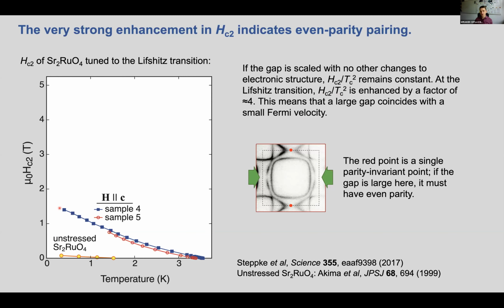So I guess my less sophisticated view of it as an experimentalist is that this rise is really very extreme, and there's nowhere else in the electronic structure, there's nowhere else in the Fermi surfaces where something rapidly is changing at this Van Hove point. This change in shape of Hc2 versus stress, in a conventional metal, Hc2 versus temperature should have a convex form, the classic WHH form. Here we see this concave form, and we know from measurements that that's a change that occurs really very close to this Lifshitz transition. So that's something unusual that occurs right around this point, and that would prompt us to really look at the place in the Fermi surfaces where something is changing sharply.